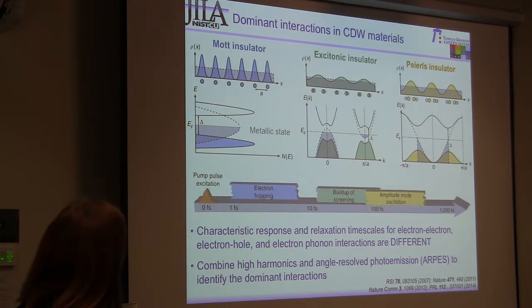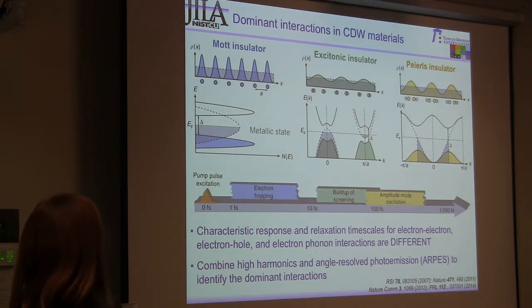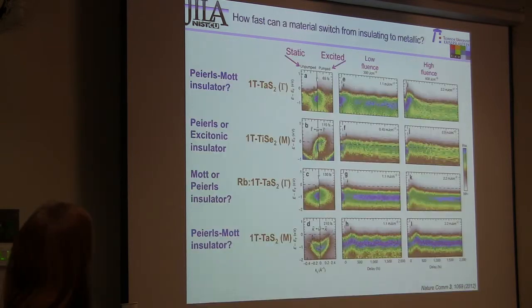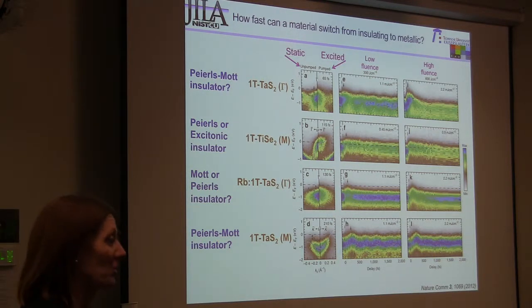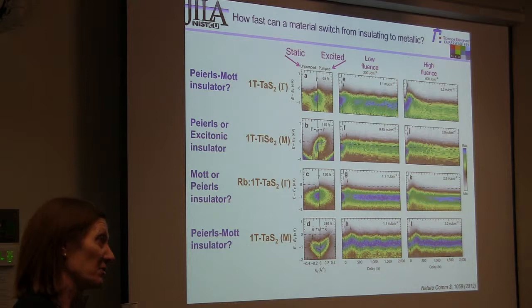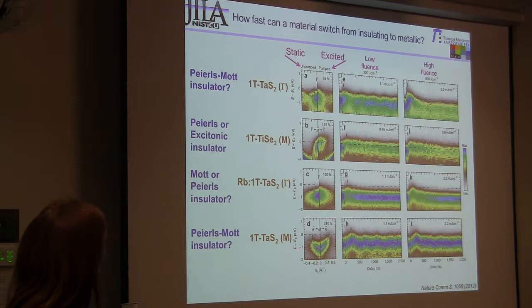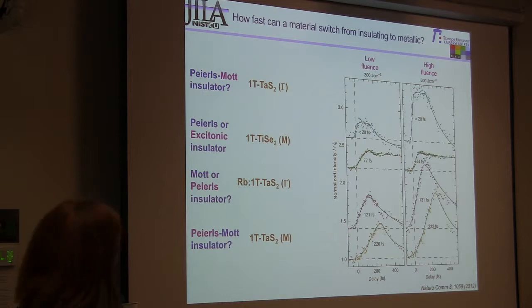And in many of these materials, whether they're an excitonic or a Mott or a Peierls insulator, why they are is not well understood. So we just did a very simple experiment, again, do the same thing, shine a femtosecond laser on the material and look at how the material responds. And we did that for different materials, essentially at low fluence and high fluence. The photoemission folks love these spectra, and it took me ages to be able to see what they were seeing in it, but the lineouts help a little.